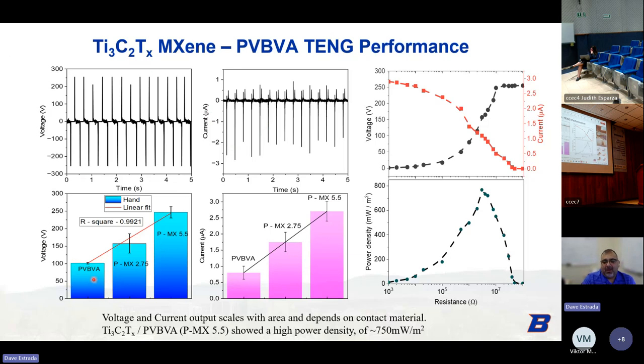We look at different concentrations of MXenes mixed in PVBVA and we see about 100% increase in the voltage amplitude, as well as the current magnitude when we go up to 5.5 milligrams per milliliter of MXenes mixed into the PVBVA. At this point, if we exceed this, the MXenes begin to crash out of the composite. So this was kind of the max concentration we could achieve. But then when we plot the voltage and current curves versus the load resistance, we can see our max power density is about 750 milliwatts per meter squared, which is pretty good for these devices.